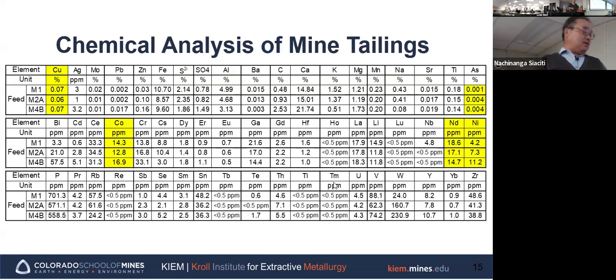And this is a chemical analysis of the tailing material. The average copper grade going into the mill these days is probably less than 1%, and I'm pretty sure Antamina's mill feed grade is around that. After all that processing, they throw away the tailings. And this is the concentration of copper: 0.07, 0.06, 0.07. We had 3 different samples. So the copper grade is less than 0.1%.